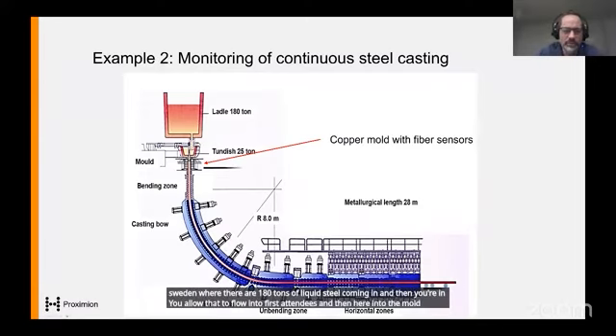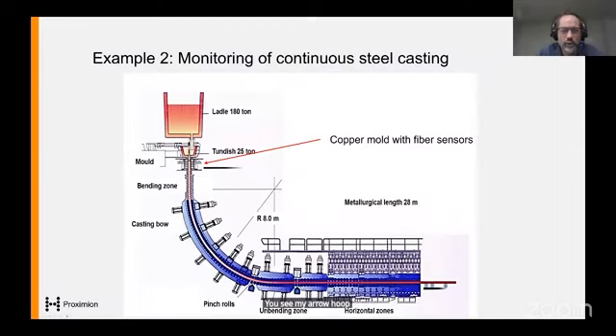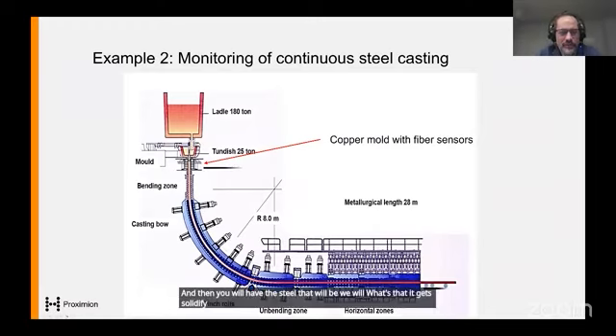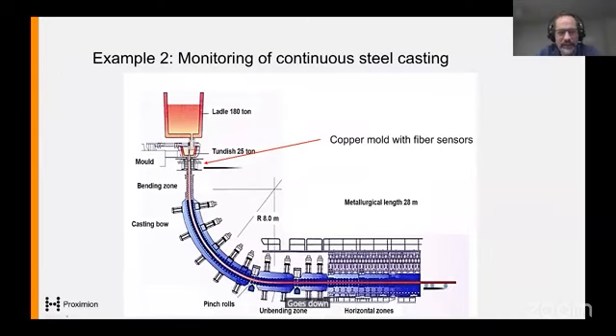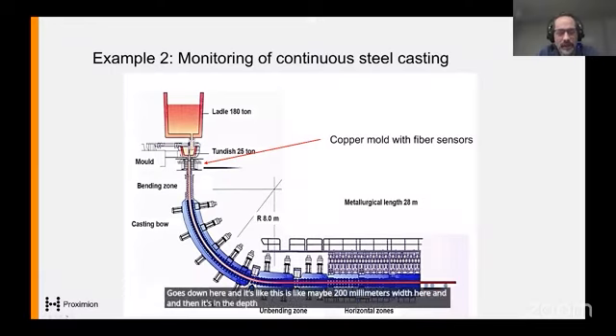You see my arrow, I hope. These are four copper plates that are cooled with a lot of water, and the steel will solidify here, at least at the surface. The steel comes out at a rate of 1 to 3 meters per minute and then goes down here. This is maybe 200 millimeters wide, and in the depth direction maybe up to 2 meters. So this is big.